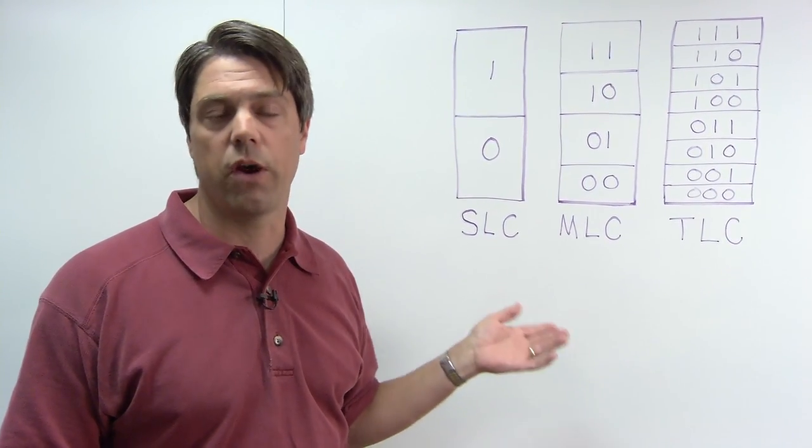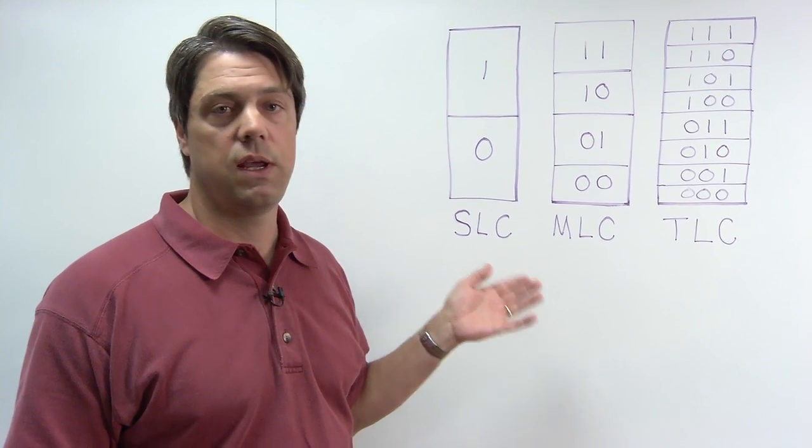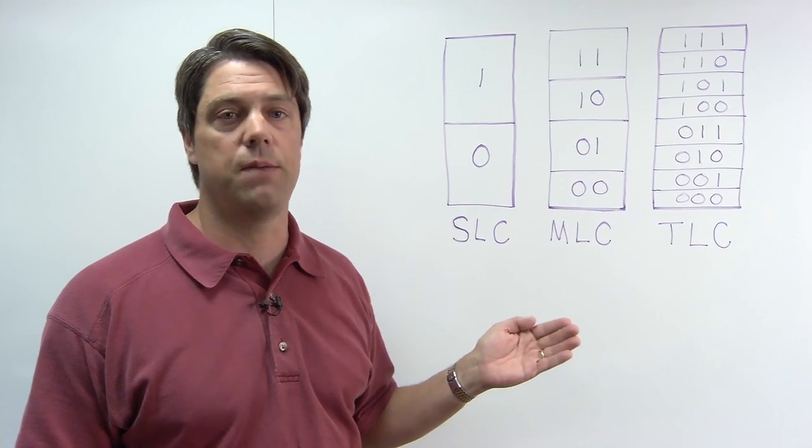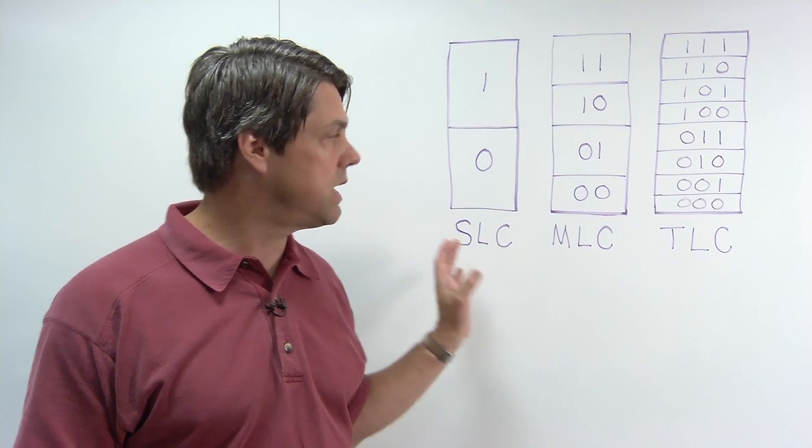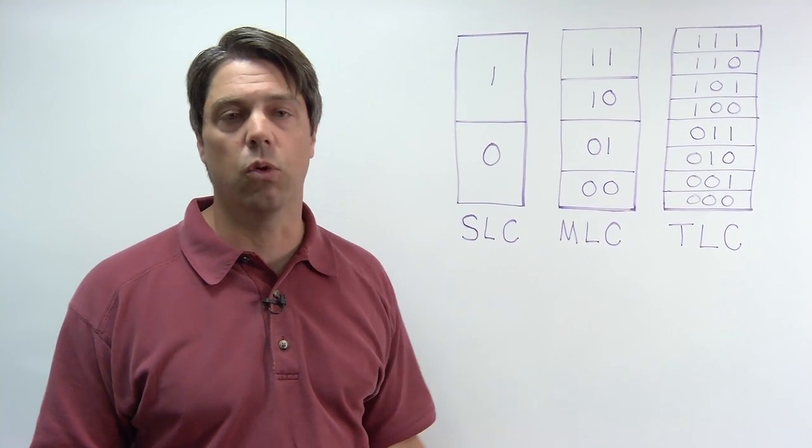There are some tradeoffs, however. The performance and the endurance, as measured in the number of times you can program the NAND, tend to degrade as we increase more bits per cell.